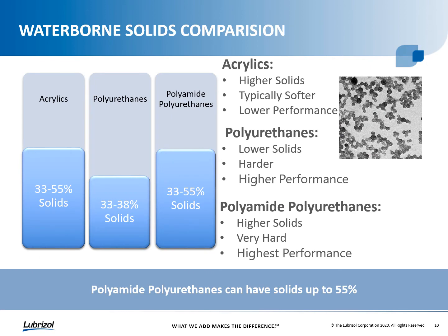In comparing the solids between your waterborne acrylics and your polyurethanes, you see some distinct differences in that the acrylics tend to be higher in solids, more in that mid 30s to mid 50s range. So typically higher in solids, but generally softer and lower in performance compared to the polyurethanes. Whereas the polyurethanes typically are lower in solids, more in that mid to upper 30s range, generally harder and higher